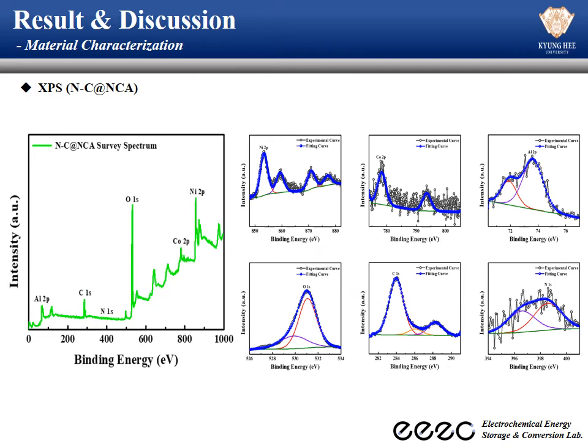And for checking valence states of the elements of N-C@NCA, XPS analysis is performed. Through the XPS data of N-C@NCA, the peaks of nickel, cobalt, aluminum, and oxide of the existing NCA were confirmed, and in addition, the carbon and nitrogen peaks were confirmed. So through this result, it can be said that a nitrogen-doped carbon coating layer was formed on the NCA surface.